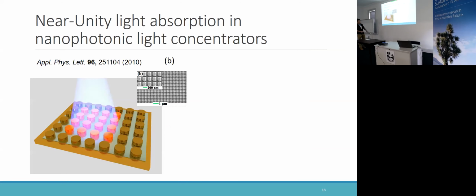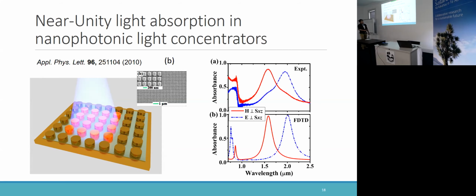Also about this structure: before, it was a single nanoparticle on the gold mirror, and we can also fabricate an array of nanoparticles on the mirror. Here is the SEM image, the scanning electron microscope image. In the spectrum, here's the experiment and here's the simulation, and we found that at certain frequencies even 100% of light can be absorbed by these structures. 100%. Of course, that's at certain frequencies, and the frequencies depend on the shape of the structures and the gap spacing between the nanoparticles and the mirror.